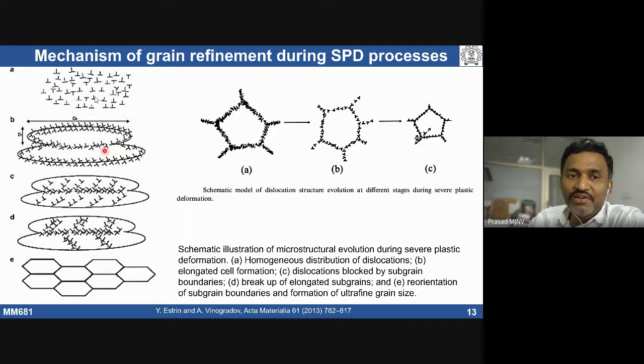So first, dislocation generation has to take place, and those dislocations have to be rearranged in the form of cells. This cell structure converts into subgrains, and these subgrains are going to get reoriented with further deformation, which can lead to the formation of an ultra fine grain structure. This is one of the established mechanisms for grain refinement during the SPD process.